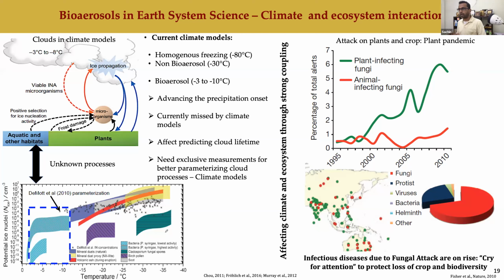Now, in any climate model which tries to predict rainfall or cloud formation, the bioaerosol schemes are not there. So the presence of bioaerosol not only preponds the cloud formation, but in the majority of cases it can even prepone the precipitation formation. Since you don't have this scheme in the models, your models are really failing to catch that event. If you look at this particular paper in PNAS, this is the ice nuclei concentration and this is the temperature. You can see that the ice nuclei concentration due to bioaerosol can reach saturation well before minus 10 degrees centigrade.